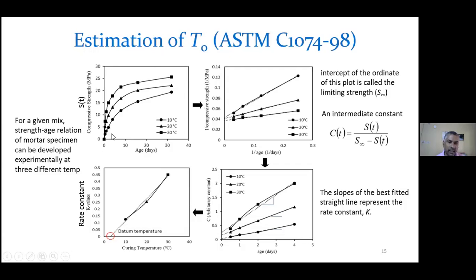And you see the first figure here. There are 4 figures. The first one shows the age versus compressive strength at 3 different temperatures as per the code. That is 10 degrees centigrade, 20 degrees centigrade, and 30 degrees centigrade. At 3 different temperatures, we can find out experimentally. We can develop this mortar specimen, keep it at different temperature baths, and then test the specimen and find out the compressive strength at different ages, up to 32 days, and we develop this plot. This is the strength-age relation, right?